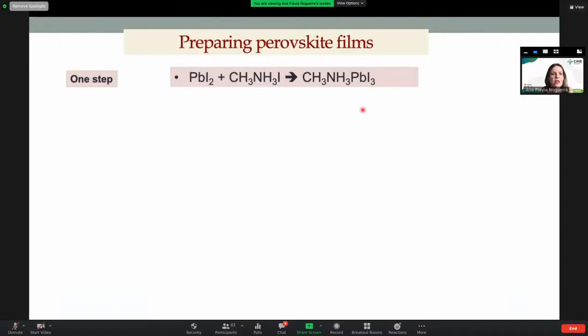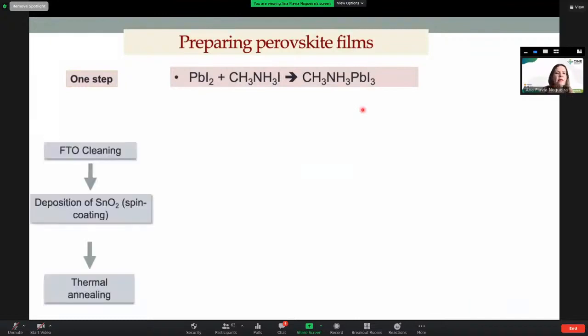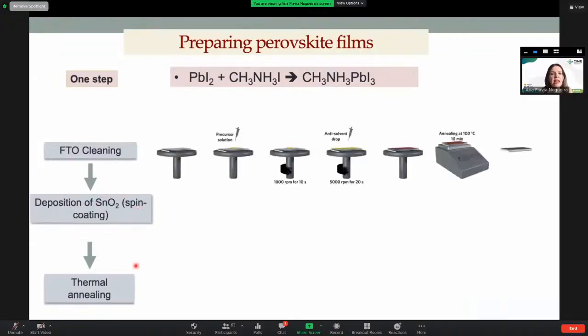So, okay, we start cleaning the substrates. In the case of the standard configuration, we deposit the tin oxide by spin coating, for instance. Then we have a short time of thermal annealing. And then I take this film here.